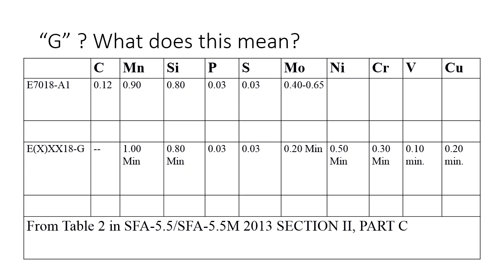Well, if we order some 7018G, we've got to have a minimum of 1.00% manganese, 0.8% minimum silicon. There's our phosphorus and our sulfurs. And then it's telling us what we have to have for the rest of our alloying elements. We've got to have a minimum of 0.2 moly, 0.5 minimum for nickel, 0.3 for chrome, 0.10 for vanadium, and 0.2 minimum for copper. So as long as they reach those, this thing can be all over the board.